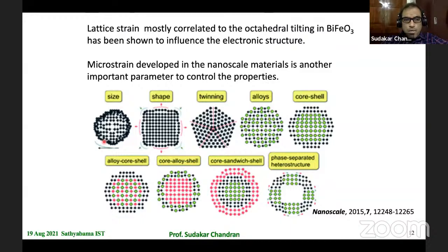Okay, in addition to what I discussed, the defects, how it can have influence on the electronic structure and so on, we can have other kinds of defects which basically introduce lots of lattice strain, specifically in the nano materials. So this particular picture, of course, taken from this reference, you can see that depending on the size, the surface atoms are relaxed. They don't have any more atoms to bond from the outside. Therefore, the energy has to be relaxed, and it puts a lot of strain within the crystal, and this is what we call the microstrain.